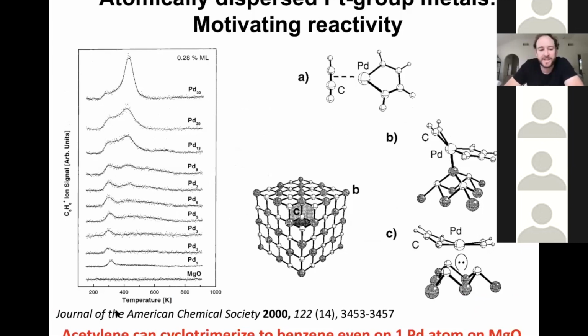I tried to pick some surface science literature as well, just to show that this has been done in many different fields. This is a paper from Uli Heiz's group in 2000 or so, where they were looking at size-selected clustered palladium deposition onto MgO. They were doing acetylene TPDs from this system. And what you could see is at low temperature, acetylene would cyclotrimerize into benzene, even on 1 palladium atom on MgO. So I think the title of this paper is 1 atom is enough, that these sorts of structures where you can shrink active metal active sites down to the limit of 1 single metal atom may have interesting selectivity, as in the previous slide, and also can do relatively complex chemistries.